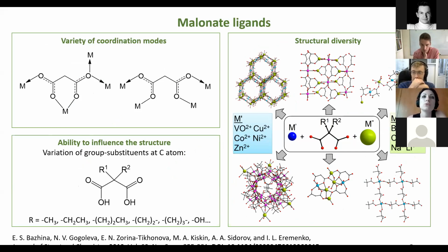Carboxylate ligands are widely used for the synthesis of paramagnetic compounds due to their coordination diversity. In particular, anions of malonic acid often exhibit chelating coordination and form with metal atoms stable bis and tris chelate units, which can be connected to other metal centers via two carboxyl groups in different bridging coordination modes, giving rise to polynuclear molecules and coordination polymers. The existence of substituted analogs of malonic acid makes it possible to affect the structure of the obtained compounds by varying the substituent at the carbon atom.